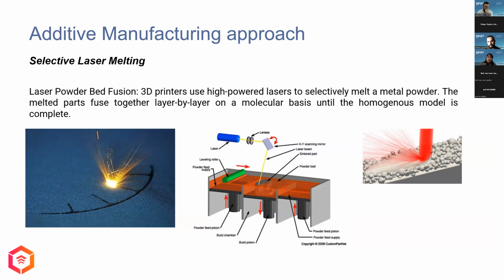Selective laser melting consists of an enclosed machine with a powder bed. A laser scanner with a detectable lens melts material into complex shapes, and when passing between layers, a plunger lowers the part down, and the machine applies a new layer on top of the previous one, and melts a new layer of material. Also, these closed chambers make it easier to work with inert atmospheres and more reactive materials like titanium and aluminum.